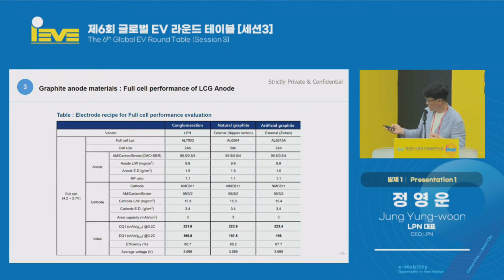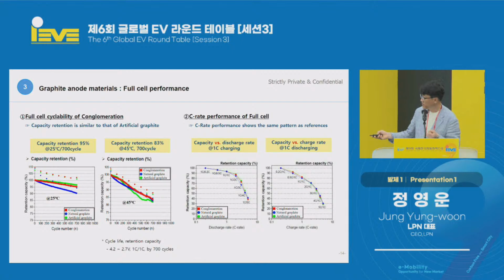Full cell test. These are the test conditions. For natural graphite, we used Nippon Carbon graphite. At 25 degrees, Nippon Carbon graphite at 700 cycles shows capacity drop, and this is within the deviation. Our anode and artificial graphite show this kind of pattern. After 700 cycles, the capacity retention was 83%, and it was much more stable at higher temperature.